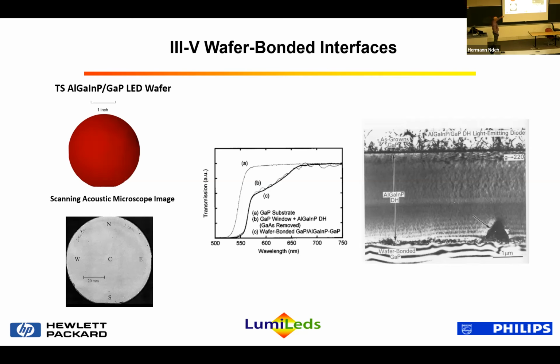This is a transmission electron micrograph of an LED structure. And what you see, this structure is initially grown on gallium arsenide. We remove the gallium arsenide and then wafer bond the gallium phosphide. On top of it, it has a gallium phosphide window. That's why we can handle the wafer. And that window is about 45 microns thick. So there are lots of inclined dislocations in the epitaxial gallium phosphide. But at the wafer bonded interface, they're nominally all edge dislocations. The one exception, and this is purposely put in here, is if you did it under conditions that were too hot, you would see decomposition at the interface, and we would actually via mass transport get crystalline regrowth, albeit oriented in a different direction. So you have to stay under the temperature for decomposition to avoid getting these types of defects in the crystal structure.